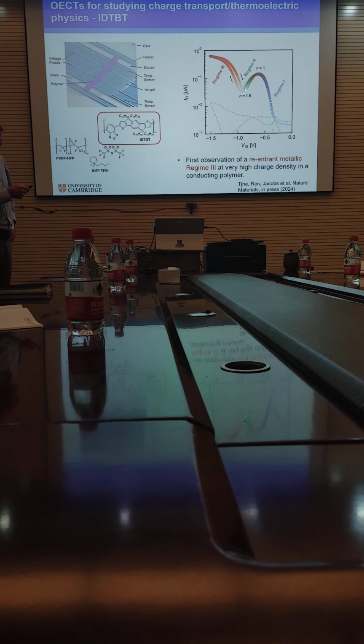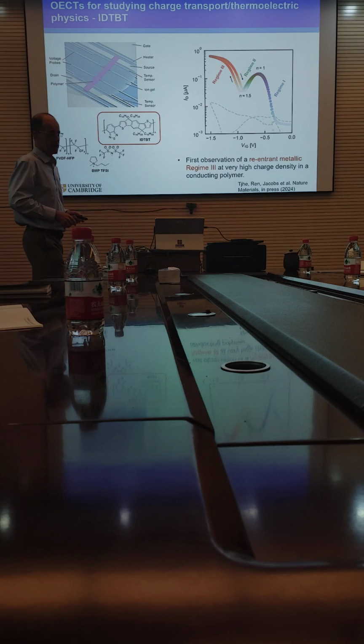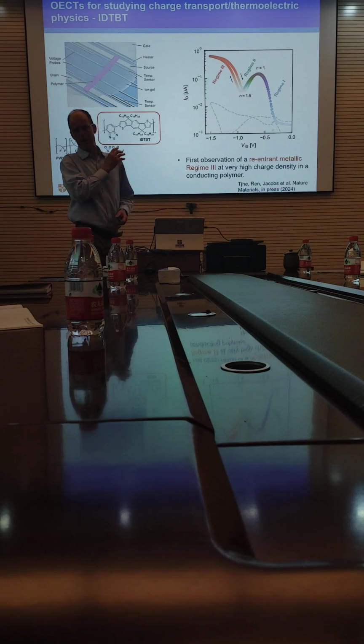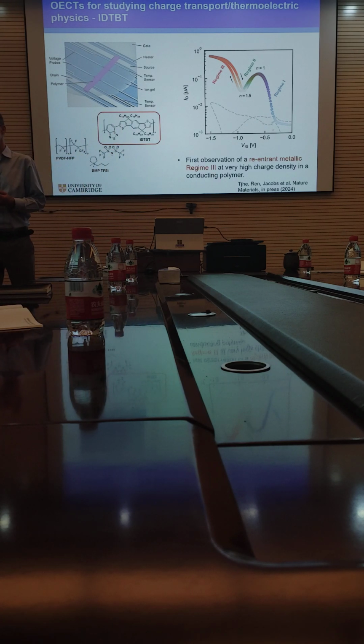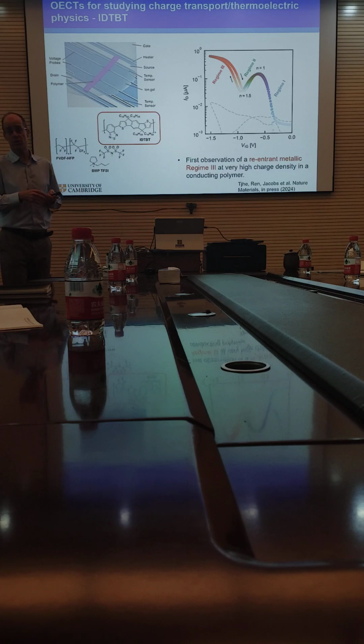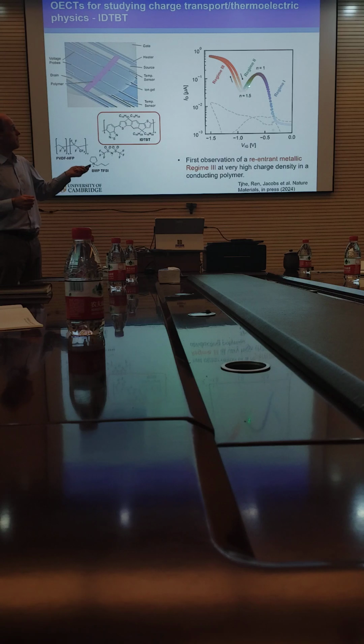But if you push even further, at some point, the conductivity rises again. And this hadn't been seen before in a conducting polymer. So this re-entrant metallic regime is a new observation. And this immediately excludes a few possibilities. The explanation I've given before, that the electron-ion interaction at high ion density localizes the charges, is unlikely to be the reason here, because why would the charges suddenly become delocalized again if you push even more ions in? It's unlikely. Also, the microstructure explanation is not likely to work because, if this regime is due to the polymer getting more disordered, why would the polymer suddenly become more ordered again as you push even more ions in?